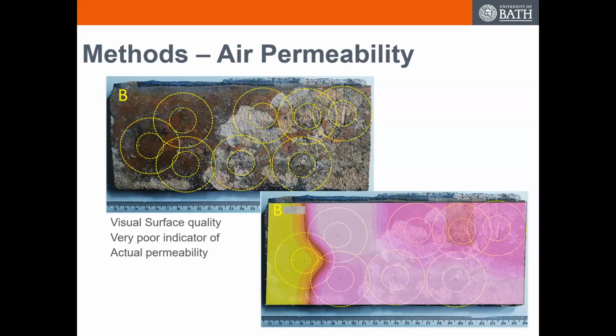A lot of the surface damage is quite often superficially surface. Quite often cracks or visible holes were there when it was fired. And at the microscopic levels we're talking at, the terracotta is sealed on the inside of that crack. It's just a continuation of the fireskin. So the visible defect doesn't necessarily tell you much about how it's performing, which is a bit annoying.